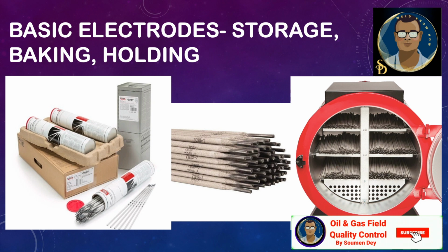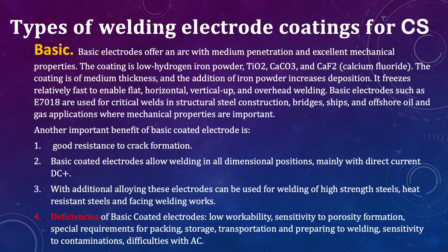Basic electrodes such as E7018 are used for critical welds in structural steel construction, bridges, ships and offshore oil and gas applications where mechanical properties are important. Another important benefit of basic coated electrodes is good resistance to crack formation. Basic coated electrodes allow welding in all positions, mainly with direct current DC positive. With additional alloying, these electrodes can be used for welding of high strength steel, heat resistant steels and facing welding